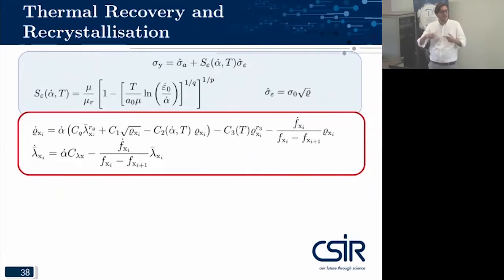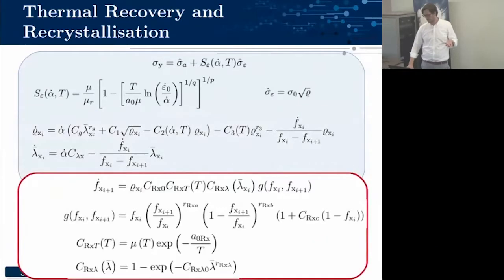And in this specific case, it also has multiple cycles. As soon as a new material recrystallizes, you can also deform that further, and that again creates dislocations within that, up to a point where it's sufficient that it again recrystallizes. So it's a staggered recrystallization, just a mean field approach to metal recrystallization. And in this case, you can see the actual rate forms of the recrystallized volume fraction, as well as how that is calculated.